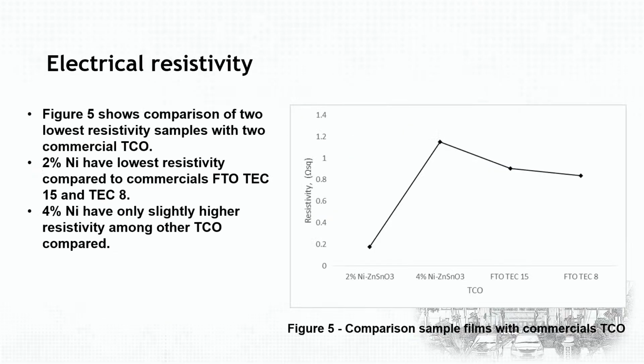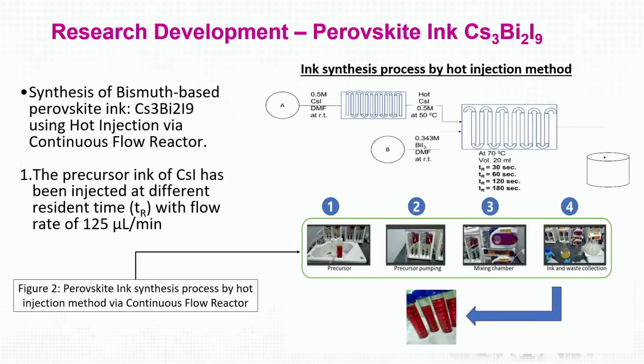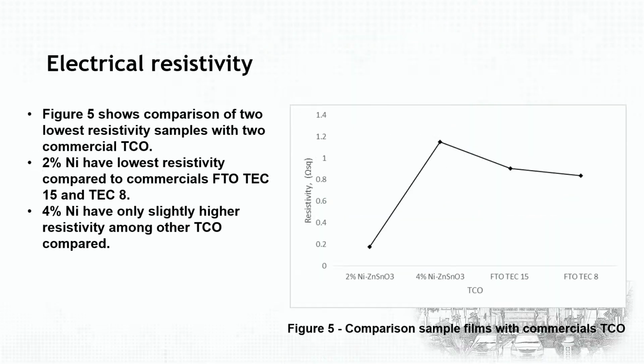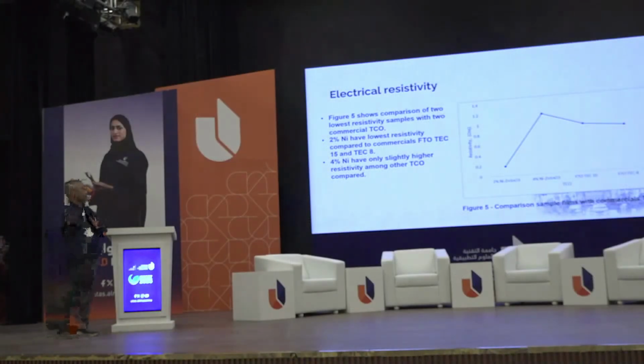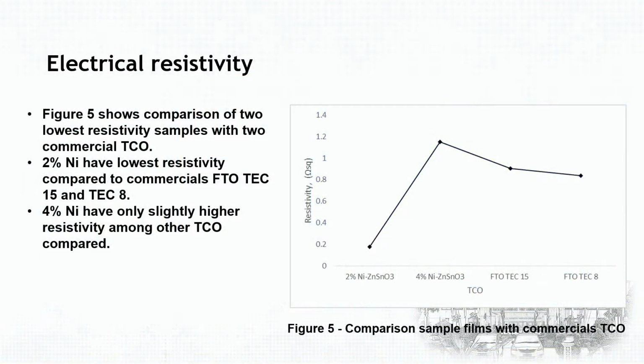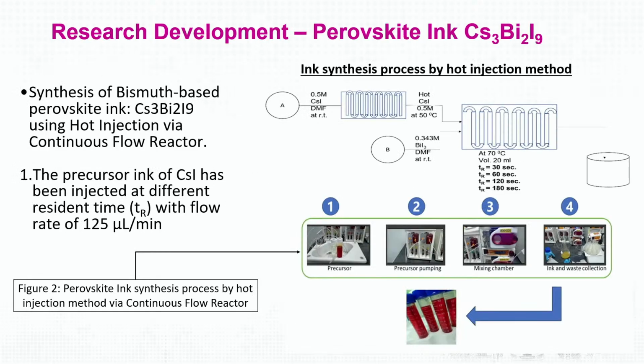Then we can see the electrical resistivity of TCO. We may observe that 2% and 4% show more viable results compared with the other doping. So we can see here by using the doping itself, we observe 2% and 4% showing the best in terms of resistivity, electrical resistivity. Then we also compare with the FTO, which is used as a standard, as shown in the chart. So you can see here that the TCO has been used as one of the alternative materials to be applied. So the result is showing more comparable to the FTO.